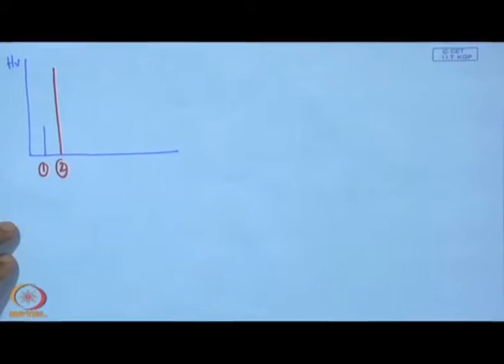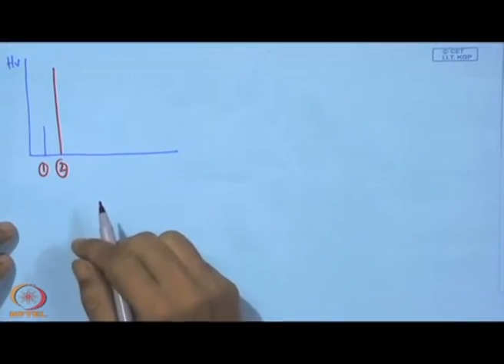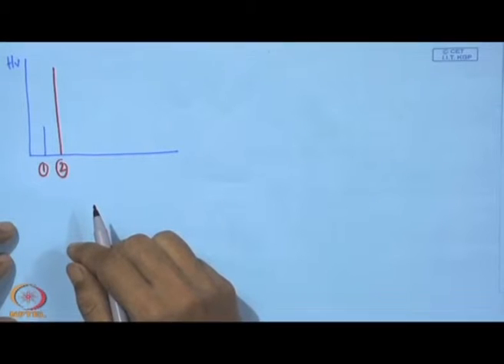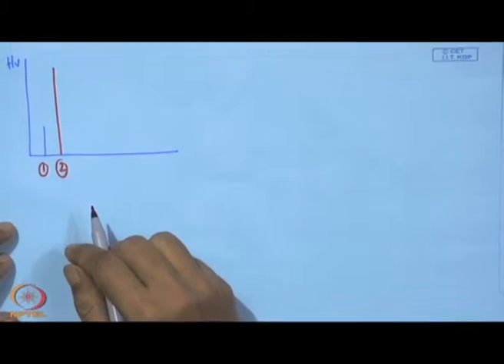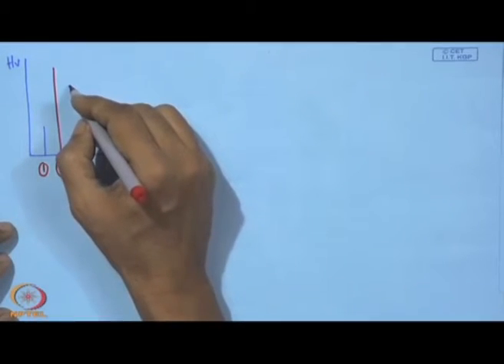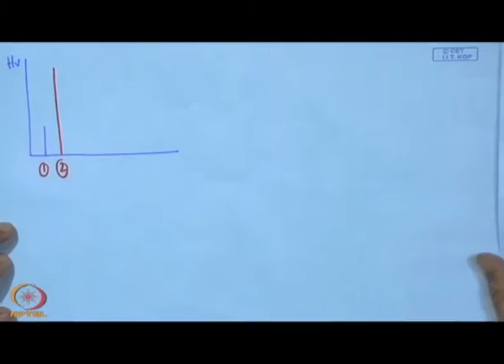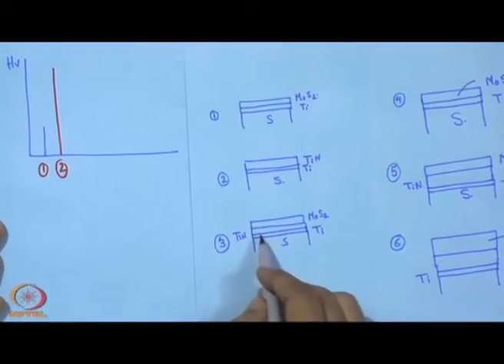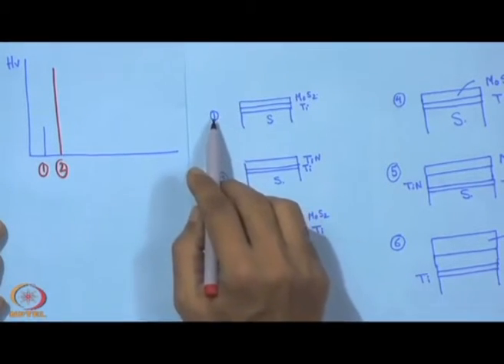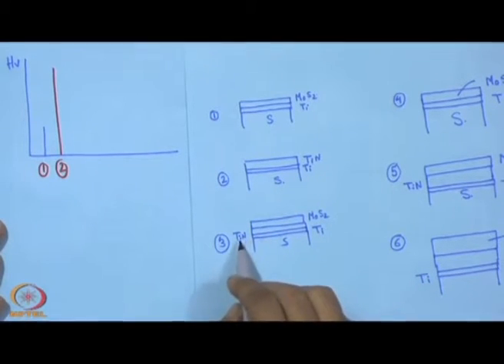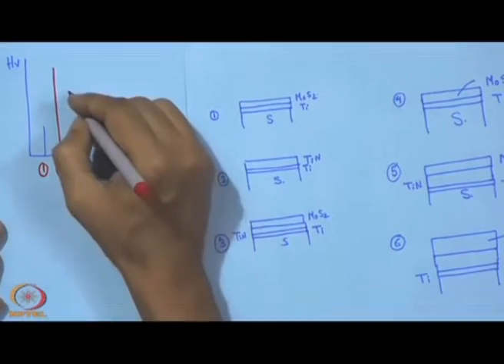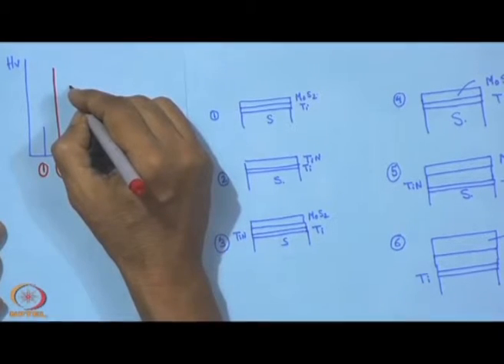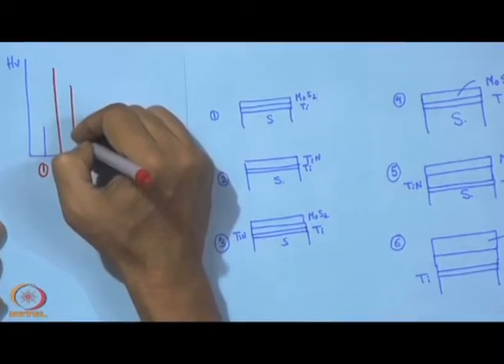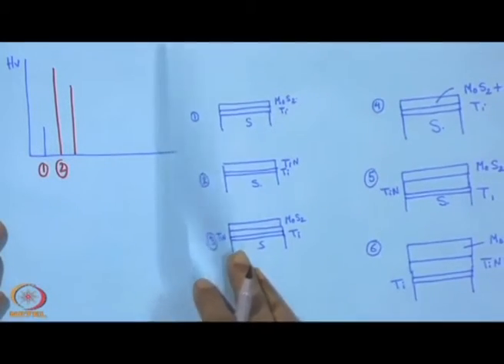So, we expect a higher hardness, followed by number 3, and this number 3 is actually MoS2 supported by this TiN. So, its hardness will fall, but we can see the bulk hardness of these 3 will be more than that of 1, because here we have a support of TiN. So, that will be somewhere little below this one, and then we have number 4.